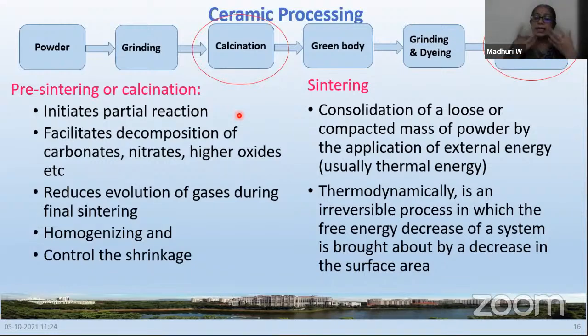And further, there may be some gases which will be releasing out of it. Assume that you are using some carbonates as your starting materials instead of oxides. When you heat a carbonate, there will be a release of carbon dioxide gas. As these gases release from the material, they may create cracks, because due to the thermal energy, the gas gets heated up and has to come out of the compacted material very fast. So in the process, it may give a crack to your material, which is not desirable, which is not a good sign for your ceramics.